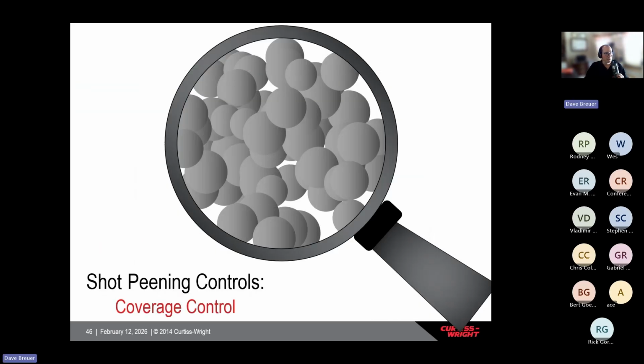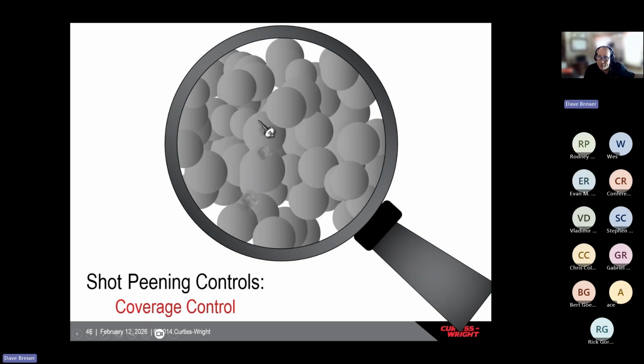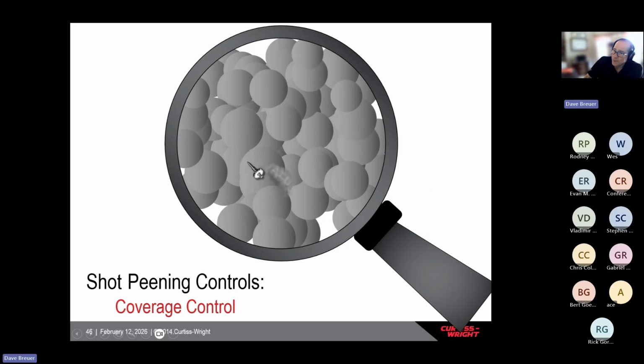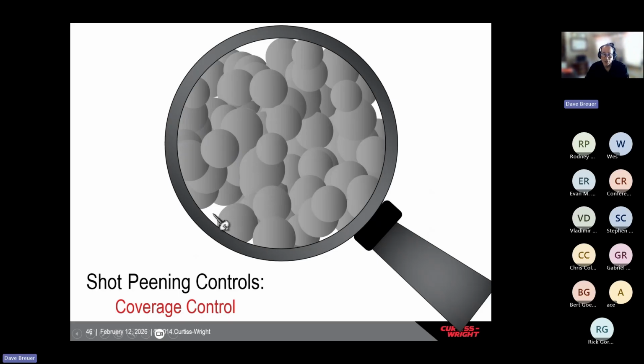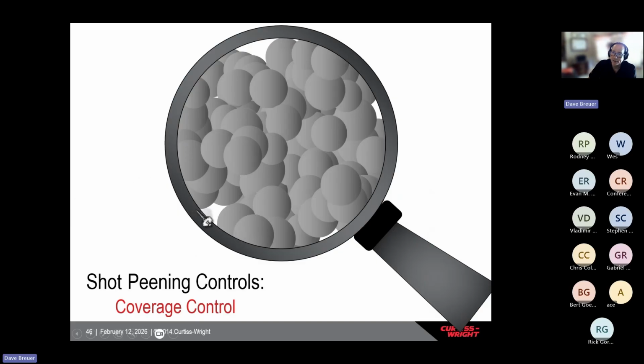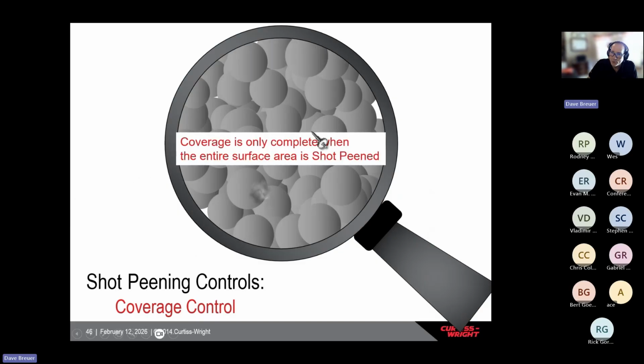The last one is coverage. Every one of these shot peening impacts leaves a dimple, and you could say there's a full shot peening compressive stress here. But when you have areas missing shot peening coverage, you have zero to reduced shot peening compressive stress. In our shops, we don't let anything leave without complete overlapping shot peening dimples, and we call that 100% covered. If you see 200% coverage on a drawing, that means you determine the time to achieve 100% coverage, then run the parts for twice that long.